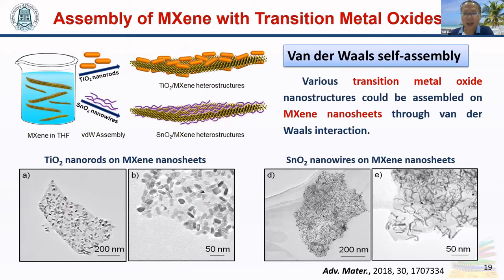The first one is van der Waals self-assembly. When we mix the MXene and metal oxide nanostructures in THF, the metal oxide nanostructures will assemble on the surface of MXenes. With this method, we prepared 2 composites. We assembled TiO2 nanorods and tin oxide nanowires on the MXene surface. We can see both of them are evenly distributed on the surface of MXene nanosheets.